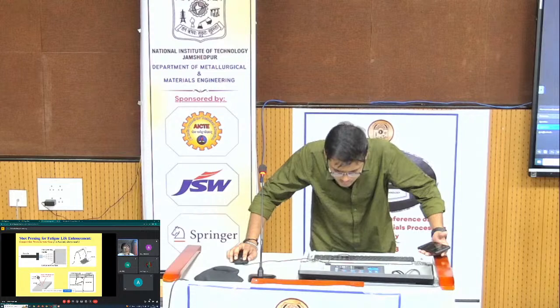Remember, we cannot lock up residual stress. After all, what is residual stress? There is no applied stress, and yet you are getting some amount of stress inside. And that can happen only up to the yield strength. You cannot have locked up stresses beyond yield strength. You cannot pour more liquid into a glass beyond the height of the glass. After that, if you keep pouring, it will only spill out.